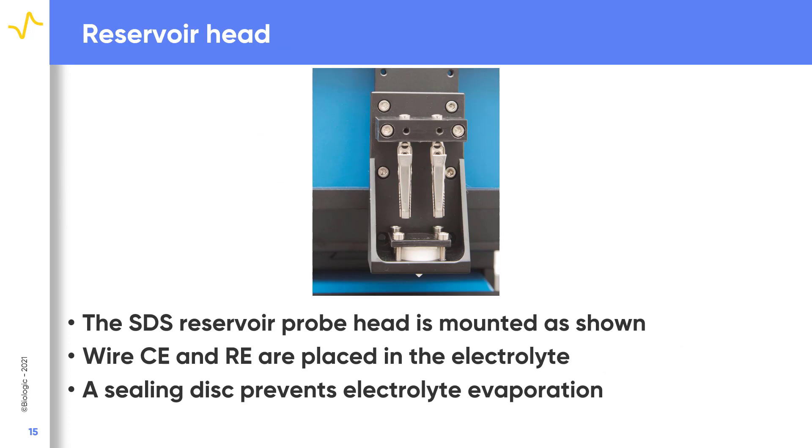The SDS 470 is also supplied with a reservoir head, which is now shown. When using the reservoir head, a wire reference and counter electrode are used. Because all of the electrolyte is held within the head, there is a risk that this could evaporate off during use. To avoid this, a sealing disc is used.